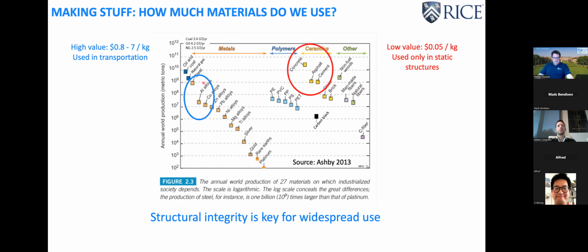But this is where there is a huge opportunity, metals. Steels start at 80 cents a kilo and they go to $5 to $7 a kilo for high-end stainless and even higher for specialty. Aluminum is $2 to $3 a kilo. Copper, it's $7 to $8 a kilo. And also these are materials that are used a lot in transportation. That's how we build our car, for example. And therefore, their high density is a major liability.